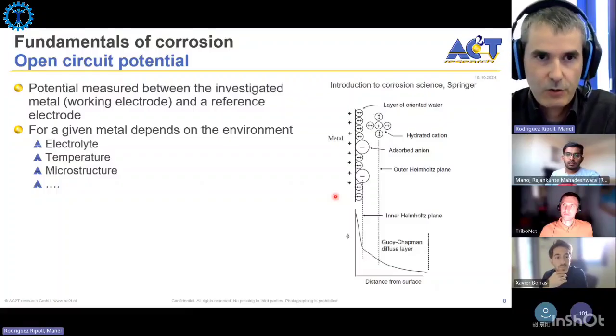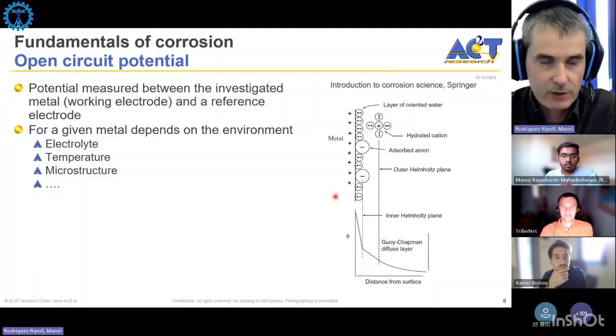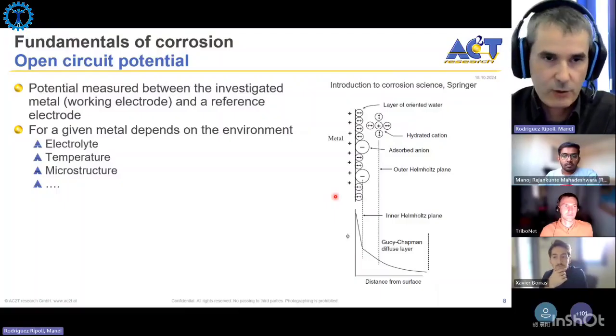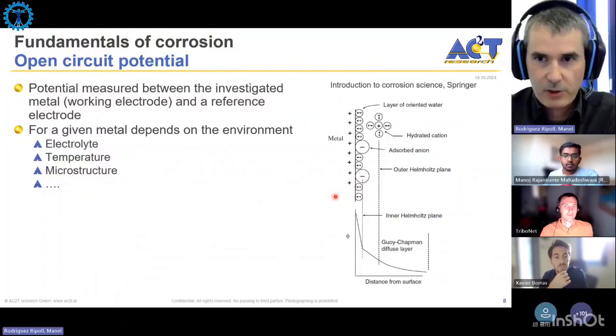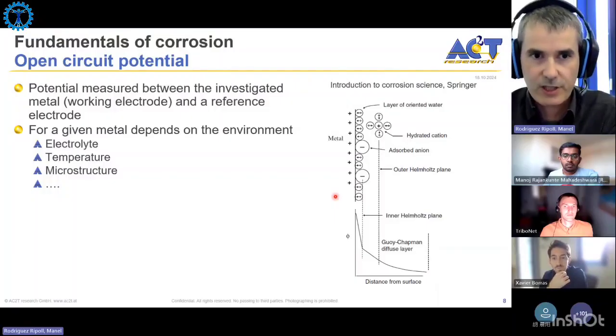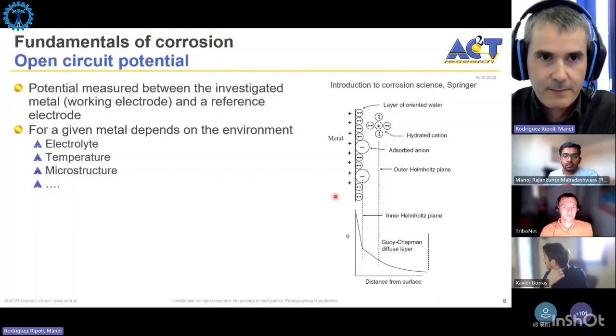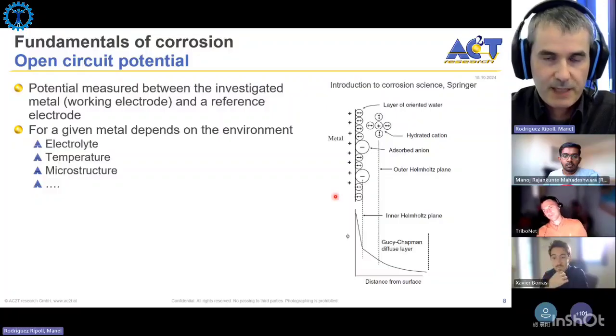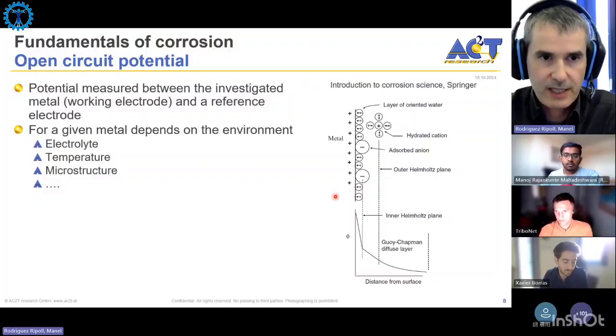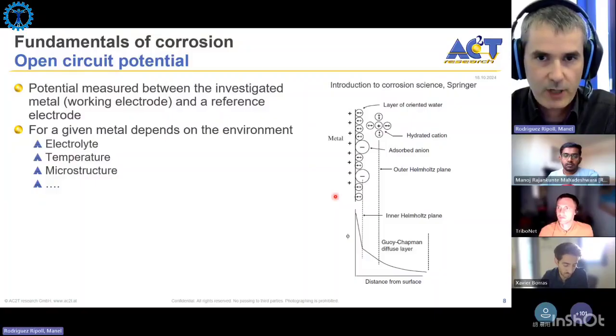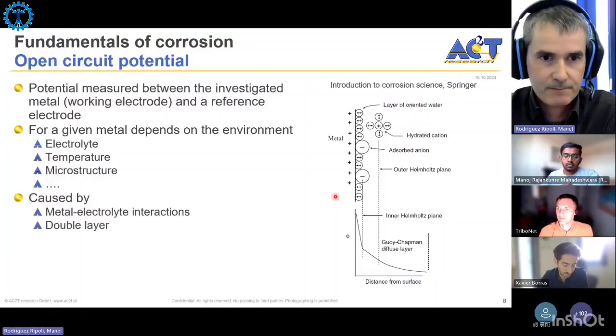And this corrosion potential depends, of course, on the electrolyte. It's not the same if we have an alkaline solution or an acidic solution. It depends on the metal itself, of course. It depends on the temperature. It depends on the microstructures. So the same material having different microstructures can have different open circuit potential. But basically, the open circuit potential is the spontaneous potential that is formed on a metal immersed in the electrolyte. The reason is what I mentioned before, this double layer and these metal electrolyte interactions.